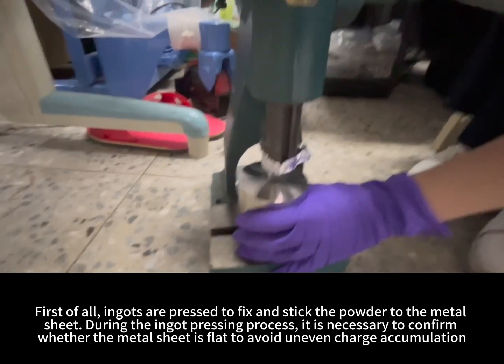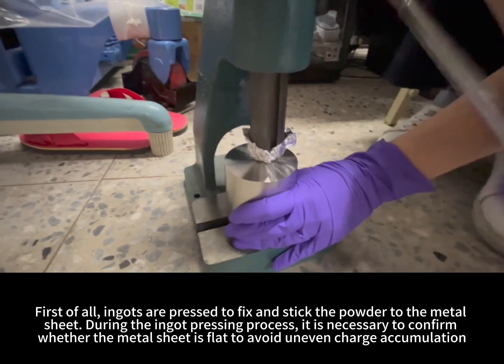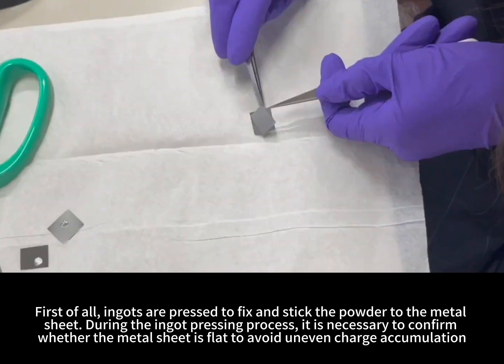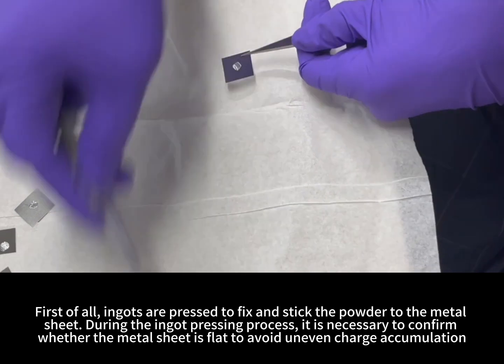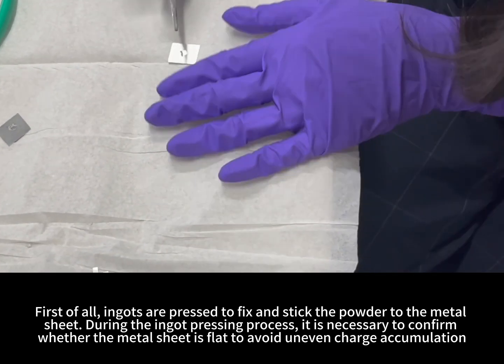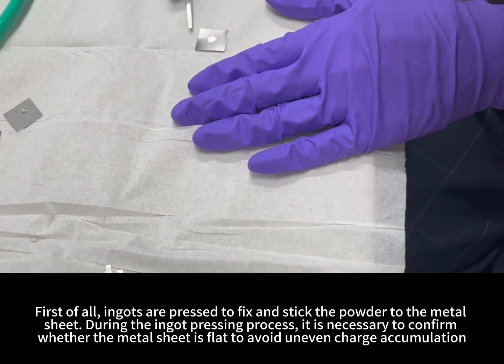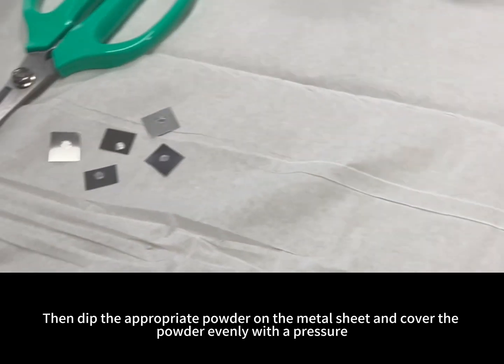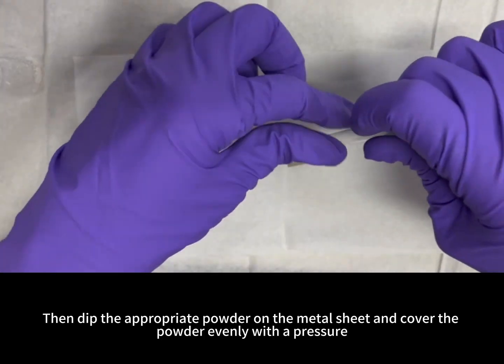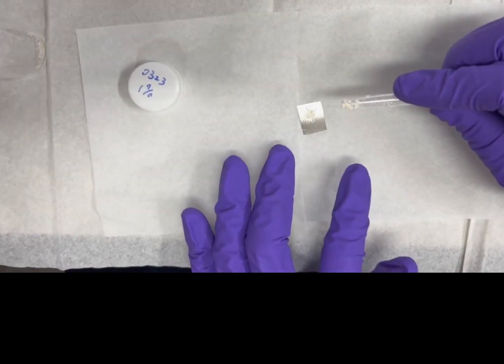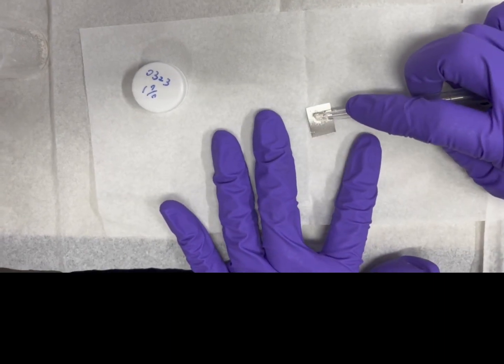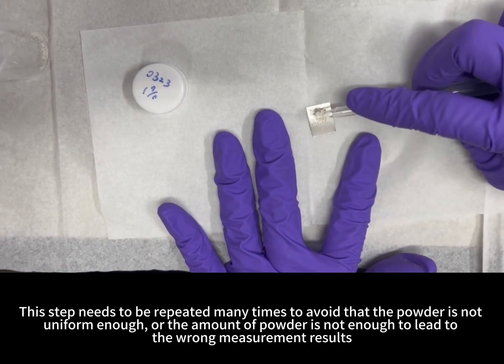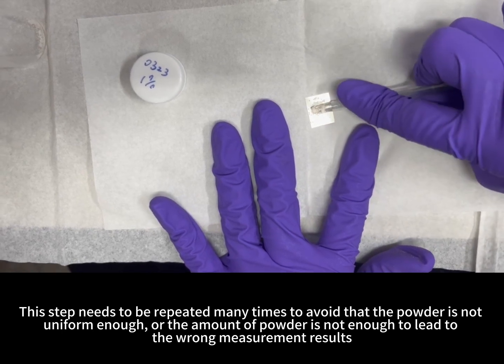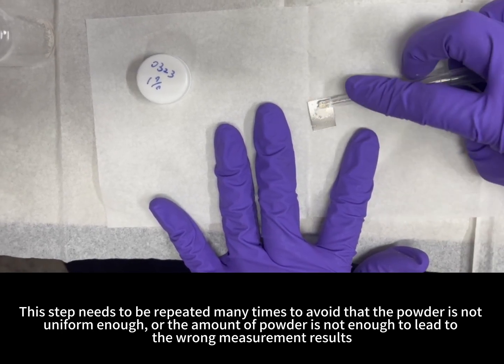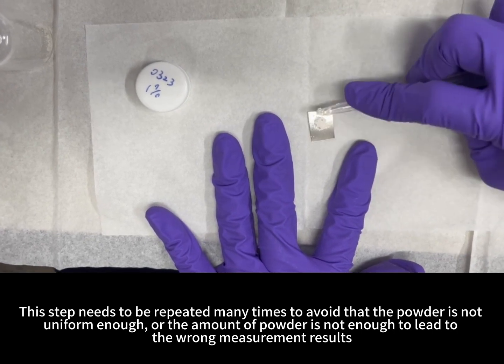First of all, ingots are pressed to fix and stick the powder to the metal sheet. During the ingot pressing process, it is necessary to confirm whether the metal sheet is flat to avoid uneven charge accumulation. Then dip the appropriate powder on the metal sheet and cover the powder evenly with pressure. This step needs to be repeated many times to avoid that the powder is not uniform enough, or the amount of powder is not enough to lead to wrong measurement results.